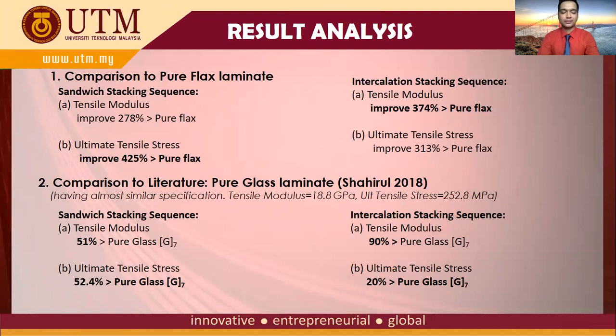As you can see from this result analysis, the effect of hybridization was remarkable for flax as it improved the tensile properties of flax. For example, the tensile modulus had improved to nearly 400%, and for ultimate tensile stress, it improved more than 400%. In comparison to the pure glass laminate, we can see that for intercalation stacking sequence, carbon flax eco-hybrid has 90% better tensile modulus. And for sandwich stacking sequence, we can see that carbon flax eco-hybrid composite is 52.4% better than pure glass in ultimate tensile stress.